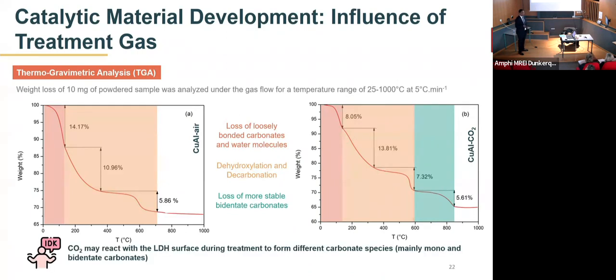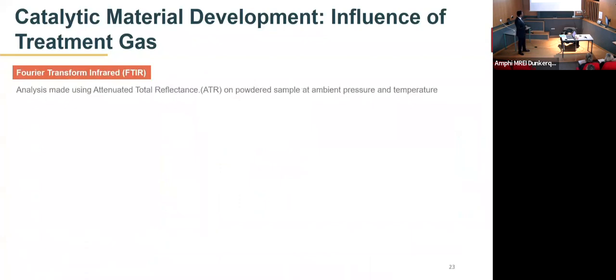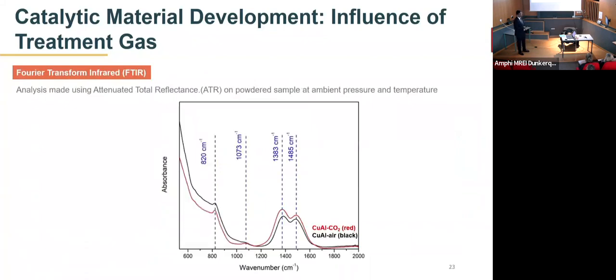So here is the hypothesis that, okay, maybe the CO2 that we use during the treatment process could have reacted with the LDH to form different species of carbonate inside the structure, which could have helped us in the reaction. In order to further support our hypothesis, we did an FTIR analysis under ambient pressure and temperature.